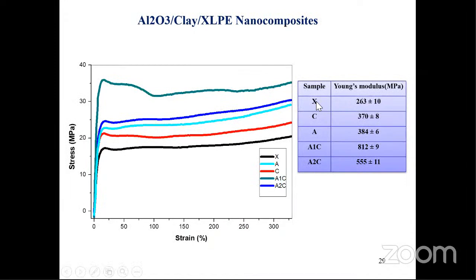This is neat XLPE, 263 megapascals. 5% of clay, 370. 5% of aluminum oxide, 384. Look at this combination, 2.5, 2.5, 812. Big jump. So we have shown to the company that if you mix two nanofillers intelligently with proper surface modification, you can get fantastic properties.